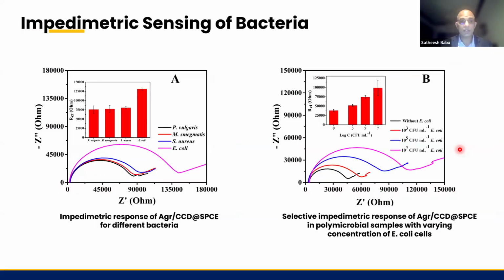And this is also tested for the other organisms. And you can see on the left hand side here, all other organisms like gram positive were actually giving the same impedance value, but with gram negative, we find a huge increase in the impedance. And the same has been studied with polymicrobial culture also. There we found that even in polymicrobial culture, when we increase the concentration of E. coli, we find an increase in the impedance. So this clearly shows that this developed system was able to detect bacteria even in a polymicrobial sample.